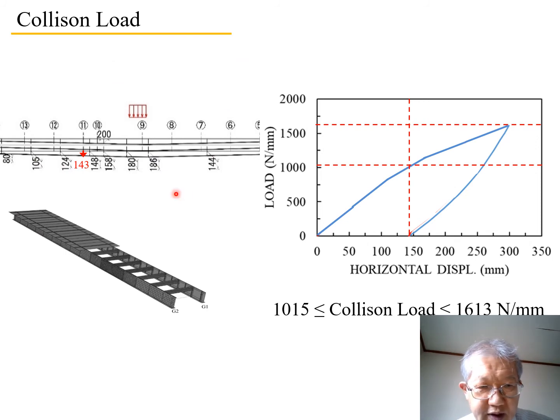Then we conducted analysis of the bridge by the finite element method using Abaqus. This is the finite element mesh. Shell elements were used except the struts, which were modeled by beam elements. And then we apply the load in the horizontal direction at around section 9. And then we obtain this displacement at section 11.